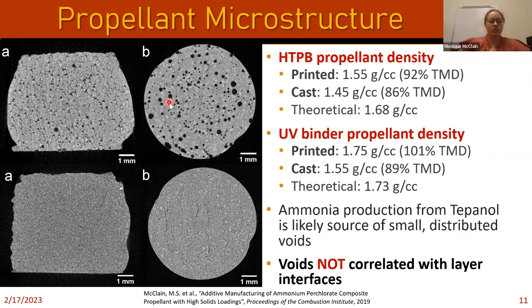Just to orient you here, these top 2 propellants had HTPB as the binder. These bottom 2 had that UV curable epoxy as the binder. These left 2 are cross sections of the 3D printed strands, and these right 2 are cross sections of the cast strands. So to note, if we're burning a propellant, the flame would be on this plane essentially.